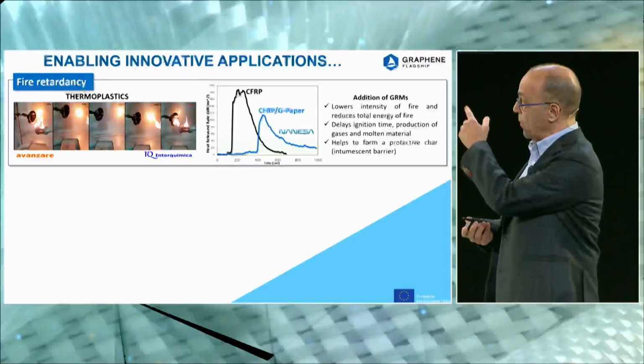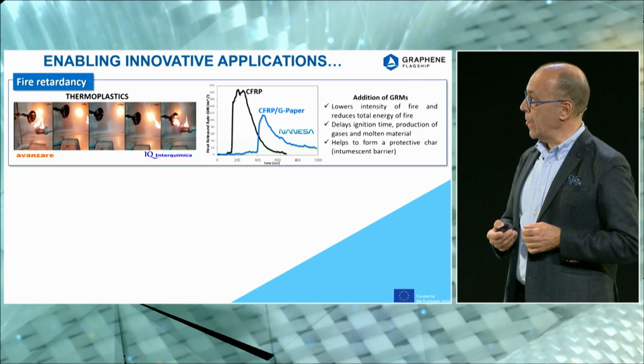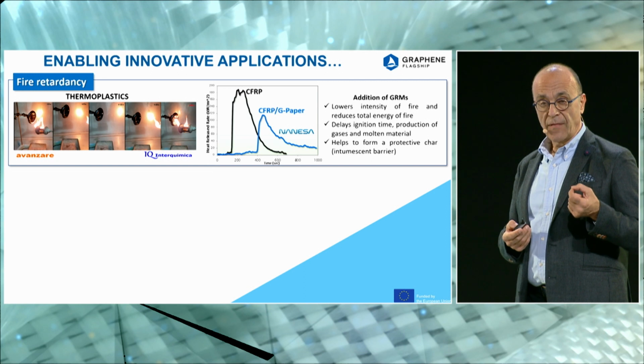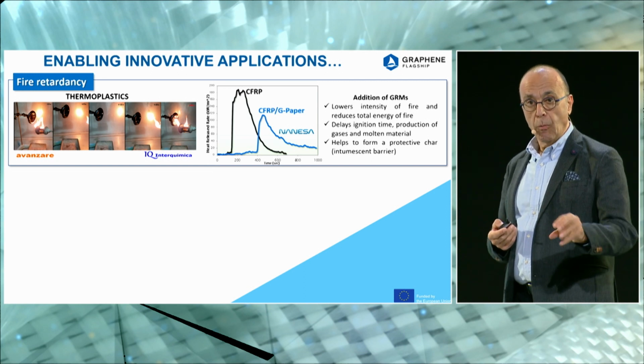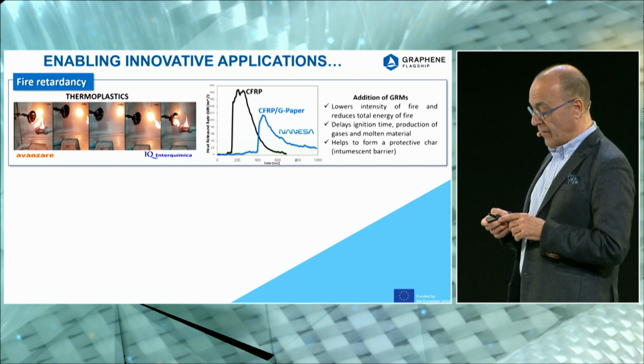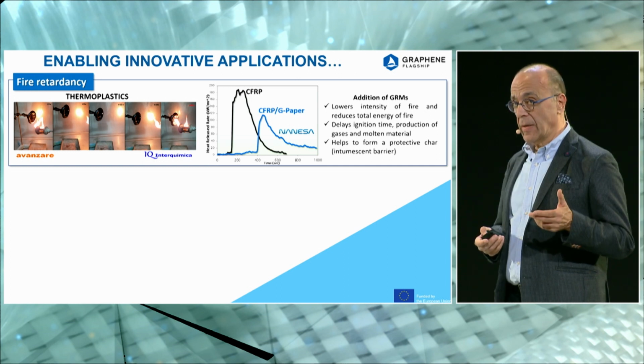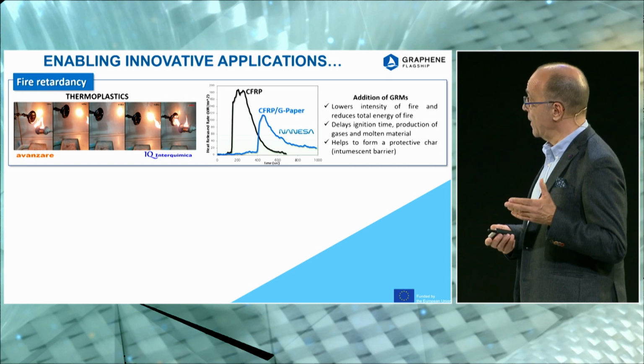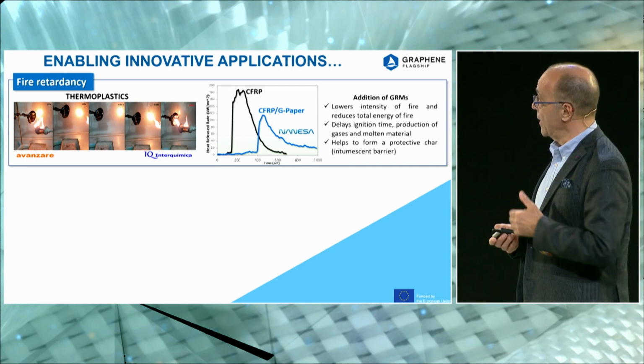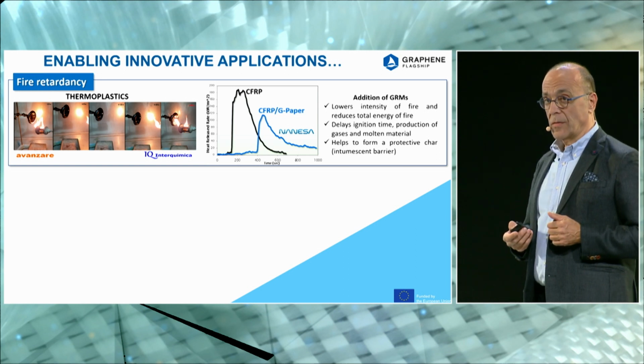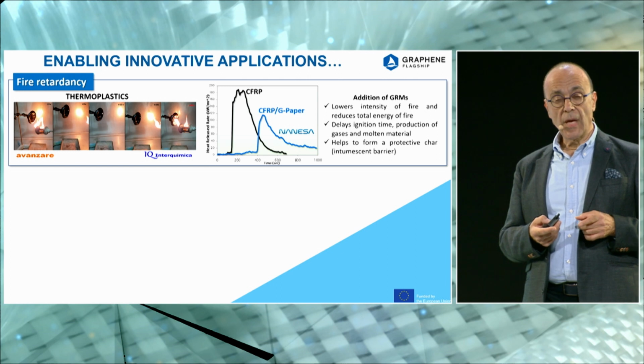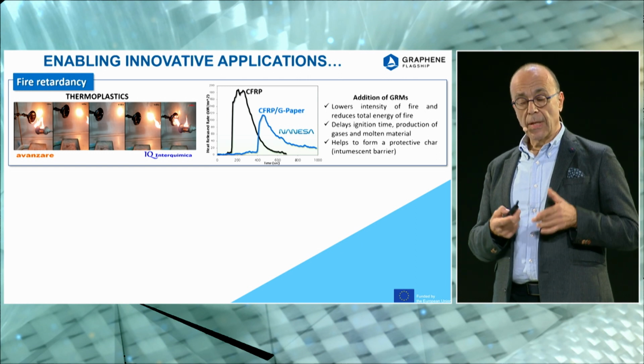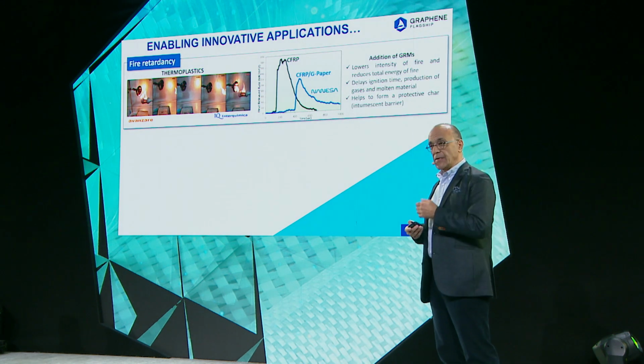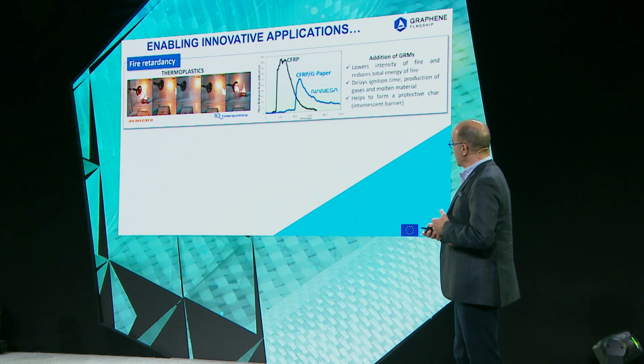And you can see an example there, where you try to burn a graphene composite knob handle. You will see you can never burn it. And on the right, you will see a carbon fiber material. This is the heat release rate prior to adding graphene, and then adding graphene. This is on G paper. G paper is a graphene paper that's produced by another company that's been developed, Nanesa, which is an Italian company that produces graphene paper, and you will see another application of graphene paper in a minute. So you will see that by adding that paper, the heat release rate goes right down.